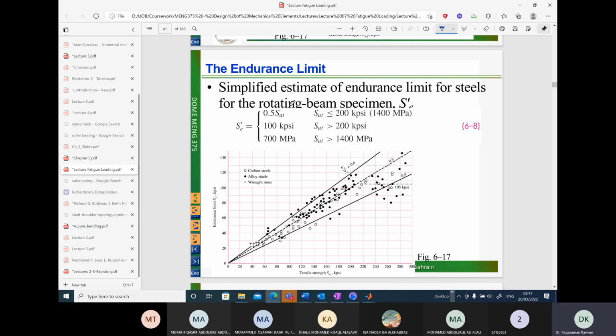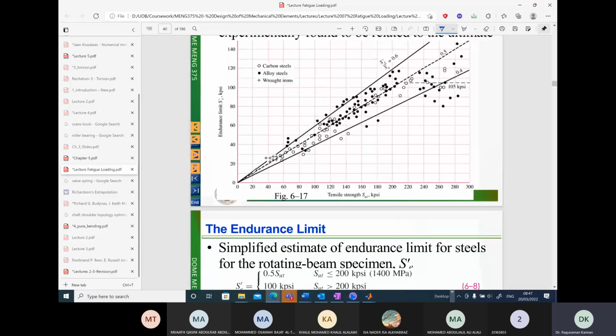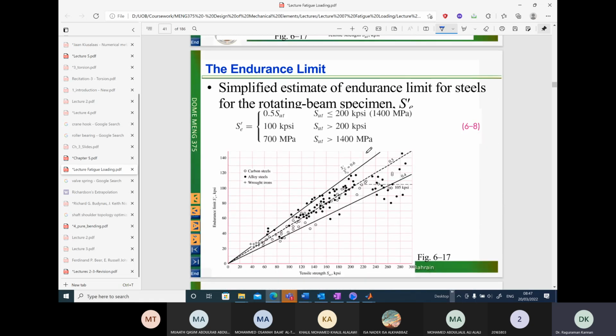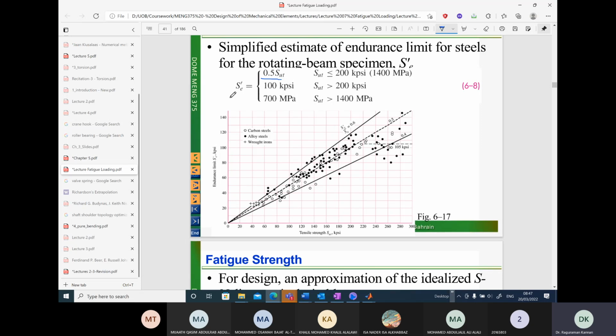0.5 times SUT is the value from 0 to, see here, you are given the graph here. Any value between 0 to 1400 megapascals, you will use the relationship 0.5 times SUT for predicting the SE, the endurance limit of steel. So if your SUT value lies between 0 to 1400 megapascals, this is the relationship you will use to get the SE value. On the other hand, if your SUT value is greater than 1400 megapascals, then you will simply take the endurance limit as 700 megapascals for steels. Okay, so this is the very first important property, and you should know how to get or predict the values from SUT values.